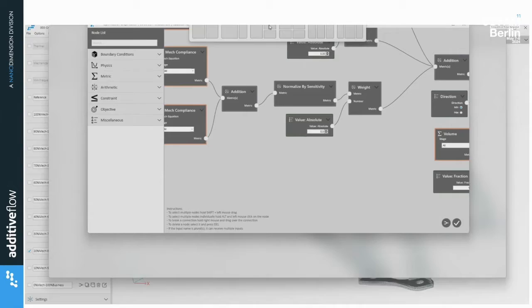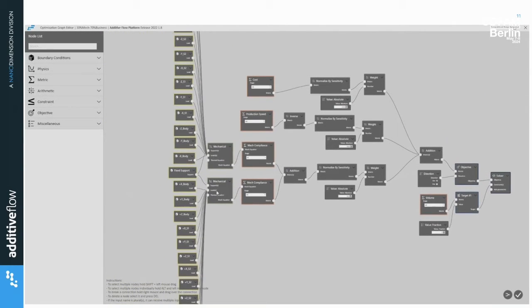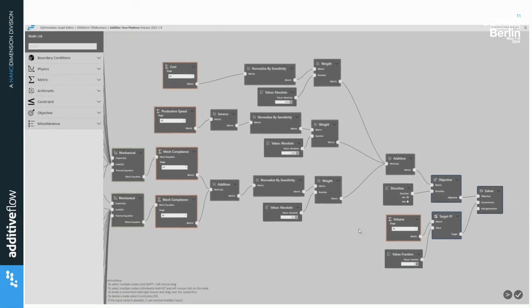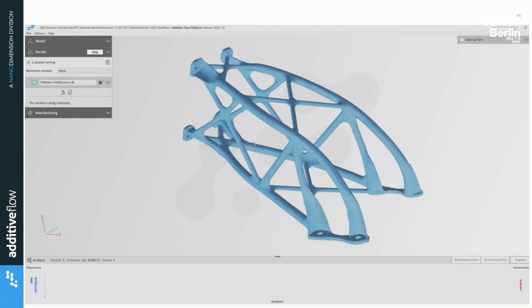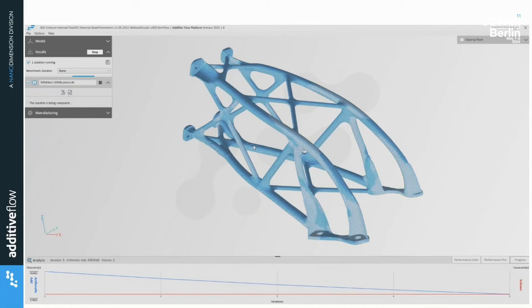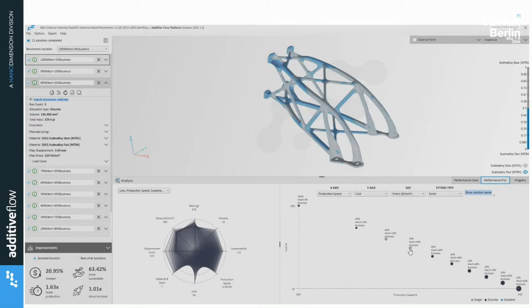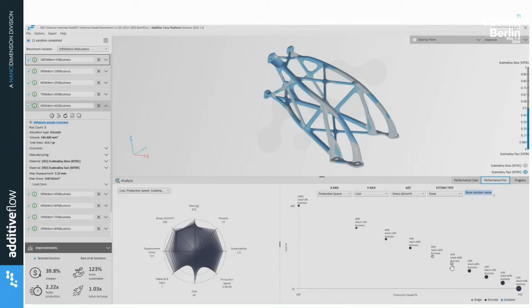How did we actually do that? We take the model and connect all the physics coming in — in this case FE map and other physics, plus internal in-house tools. We look at metrics for production and cost simultaneously, weighted as objectives. By weighting these objectives differently, we can trade off against the internal volumetric composition. You can see in the blue and gray regions our solver volumetrically allocating different process parameters in different locations based on engineering requirements, making sure parts can successfully print and meeting the cost target. The engineer can explore that map — production speed versus cost versus arising stress — instead of wasting time randomly iterating against parameters.